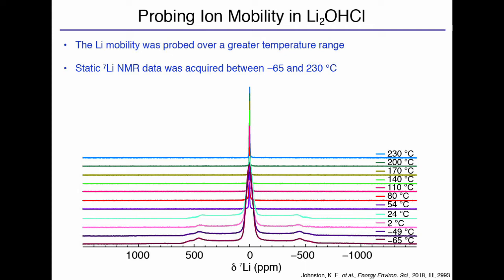Now, in NMR, we're quite limited in how much we can go up in terms of temperature. So what we were able to do was some lithium studies over a really large temperature range between minus 65 up to 230 degrees C. And what that allowed us to do is just to see how much that peak is going to narrow across this temperature range. And you can see it starts very, very broad, and then everything's on top of each other. It's really difficult to see, but it's really, really narrow.